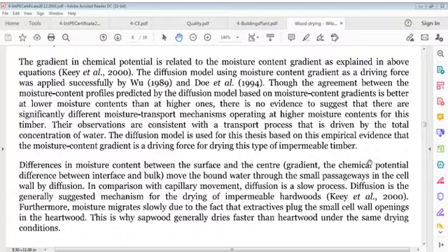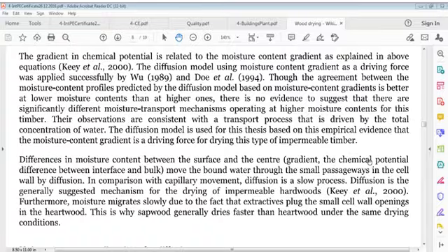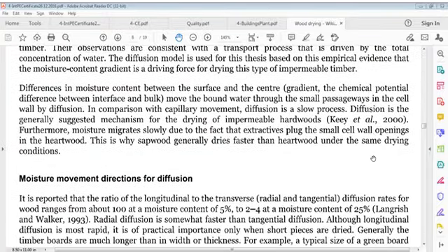Differences in moisture content between surface and center give a gradient, a chemical potential difference between the interface and bulk. Move bound water through small passageways in cell wall by diffusion. In comparison with capillary movement, diffusion is a slow process. Diffusion is generally suggested mechanism for drying of impermeable hardwoods. Furthermore, moisture migrates slowly due to the fact that extractives plug small cell wall openings in heartwood. This is why sapwood generally dries faster than heartwood. So this is what the moisture movement direction is for diffusion.